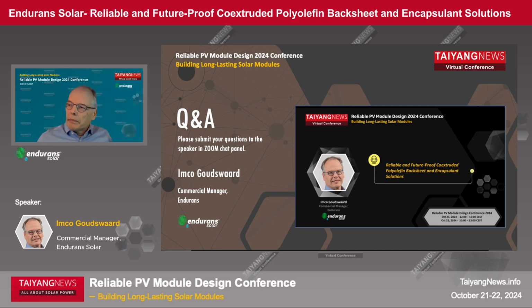Yeah, so I think transparency of glass is something like 92%, and of a commercial transparent backsheet that probably goes up to 82, 83%. And due to the haze we add to our backsheet, we get to a transmission of something like 78%. And still you have the overall power yield of 3% higher than the transparent backsheet. That has mainly to do with the rear side impact. So from the front side, we still have some reflection even if we don't have a grid. And of course that really depends on what the cell gap is. So the smaller the cell gap, the lower the added value of a grid is.